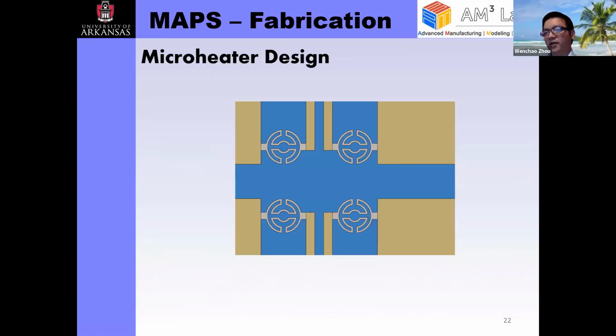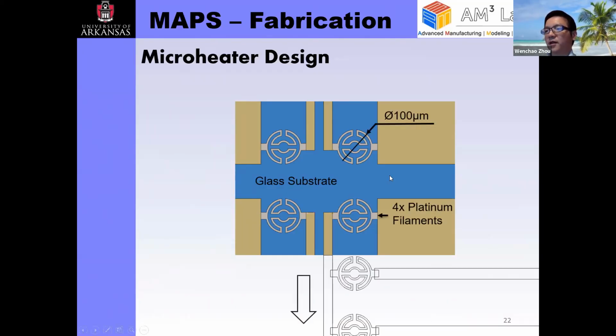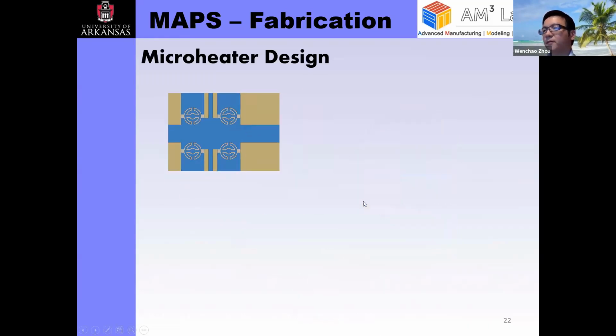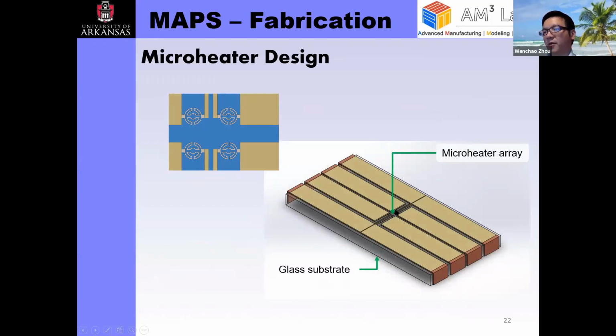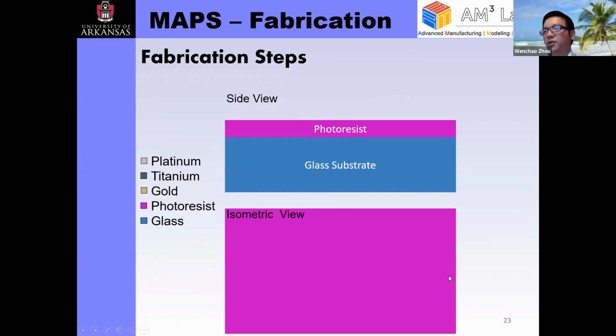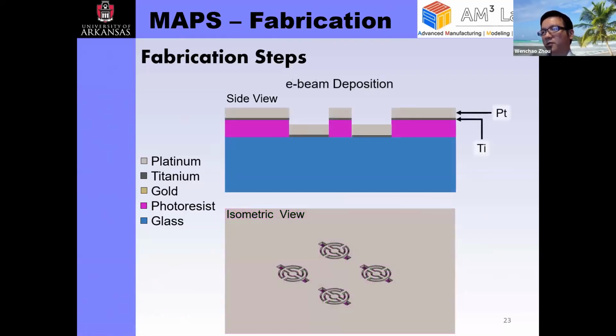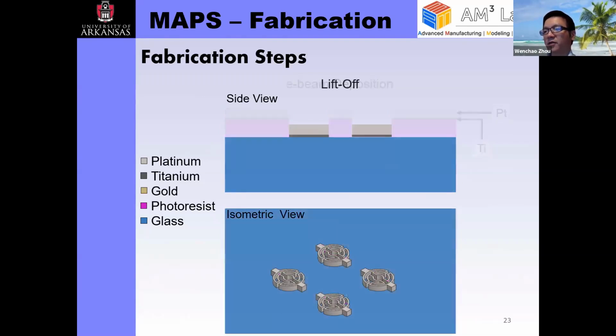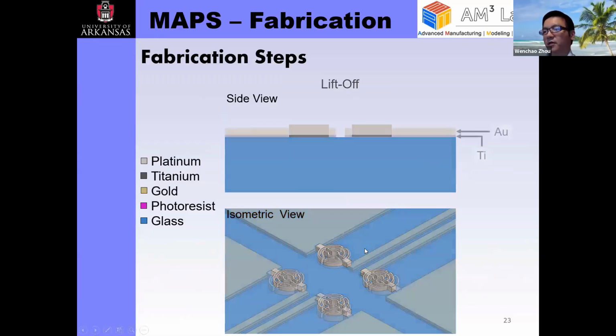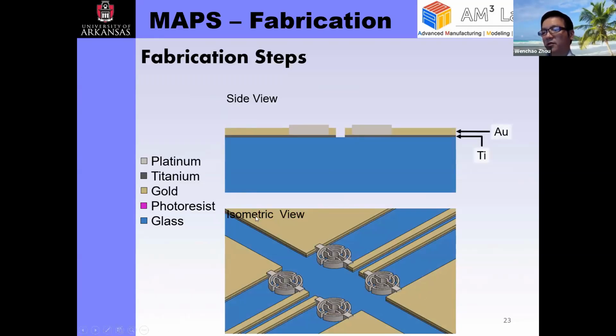So this was a simple idea, and with that idea, we started to implement and test it. We designed a small scale 2x2 array of microheaters on a glass substrate, to show how it can be scaled. But we only made 4, just for simplicity. And with that, we designed a package to put a microheater on a glass chip, with conductive leads to connect to external circuits, and also extended leads for connecting to the packaging. Then we used e-beam deposition for the fabrication, which is a simple photolithography process with deposition of titanium and platinum layers for the microheaters. In the same way you can deposit the conductive leads, for which we were using gold.